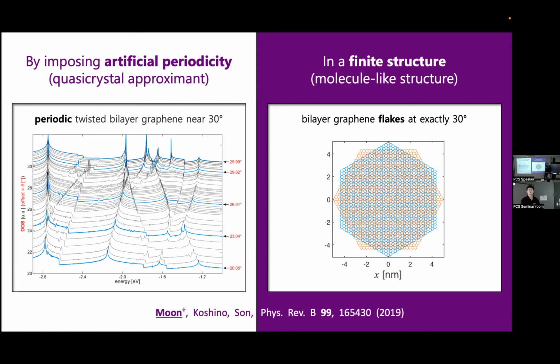So they apply the artificial periodicity. For example, if we apply this to our system, we may use twisted bilayer graphene, periodic twisted bilayer graphene near 30 degrees. For example, 29.99 degrees, they have periodicity. But you can see even a small deviation from 30 degrees gives a completely different spectrum. So it's not guaranteed that 29.99 degrees is exactly the same as 30 or not.